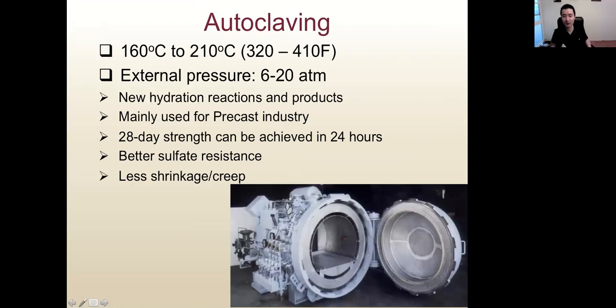Autoclaving: we put the concrete under very high pressure and very high temperature, way beyond steam curing temperature. Steam curing temperature is around 60 to 80 degrees Celsius, but autoclaving is above the boiling temperature of water, 160 degrees Celsius and beyond, with very, very high pressure.